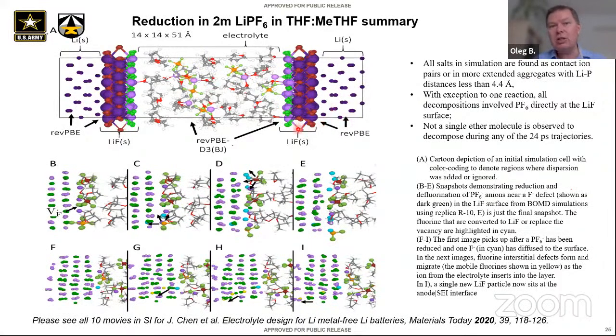What is true is that here the rates are much faster. The reactions are on a picosecond timescale instead of what you would expect, orders of magnitude faster, because of this very small passivation layer. But at least it has a chemistry of the SEI, right? And we use lots of sampling. So we're thinking initially that, yes, we're at low potentials, but with lots of samples, we get qualitatively the same picture.